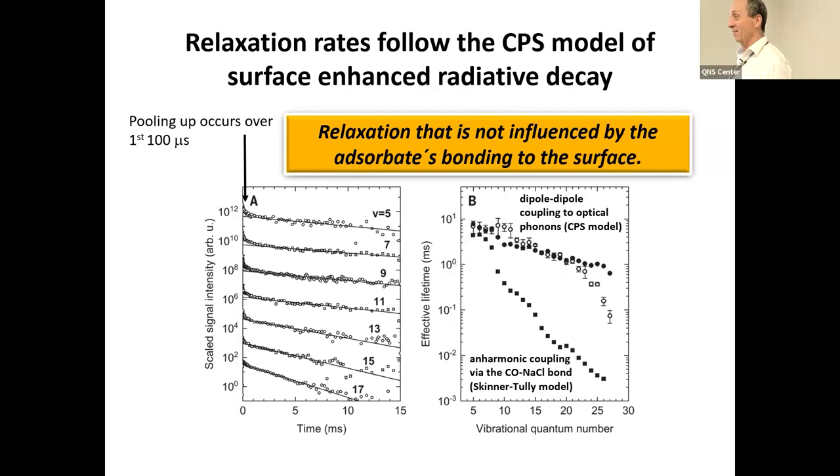Yeah. Well, one thing, it's an insulator, right? So we don't have electron hole pair coupling. On a metal, you get picoseconds because you have vibrational coupling to electron hole pairs of the metal. This is an insulator, so you don't have that. The phonons are far out of resonance with the CO stretch. And indeed, as I tried to say just at the beginning, I think this is probably the best evidence of it. These are really almost like gas phase molecules weakly bound to the solid and interacting with one another. And they give up their energy to the solid, but almost because they're suspended over the solid and they can't avoid the interaction with the solid, but it's not because they have chemical bonds to the solid, like something like hydrogen atoms on silicon with a strong covalent bond would show all these anharmonicity effects. And I think lifetimes on those systems are measured to be nanoseconds or something like that. They're slower than metals, but they're still many orders of magnitude faster than this. So this is a really different kind of behavior. And that's what I find particularly interesting about it.